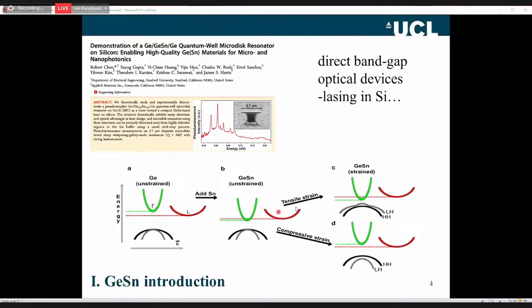However, once we make this structure with tin, we find that it's very difficult to make the structure without introducing strain. You can imagine if you etch away some of the germanium, the material has to be relaxed. But when it's in an epitaxial form, in a wafer, the germanium-tin has a larger lattice constant, so it's got to be compressed down. The germanium-tin layer is in compression, and that tends to open up the band gap. The L band shifts up. So when you grow this material, well, the bulk might be a direct band gap, but with compressive strain, the gap opens up and becomes indirect.